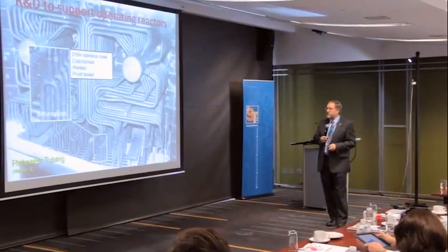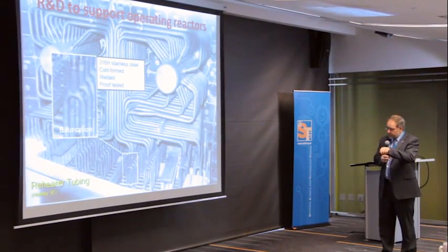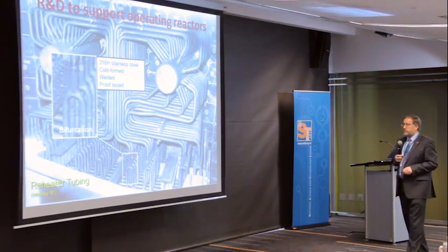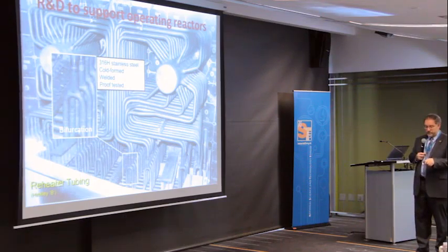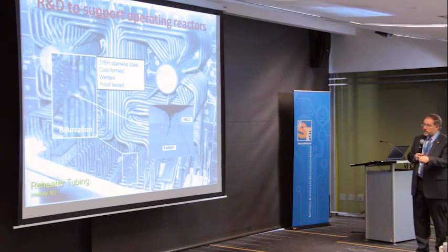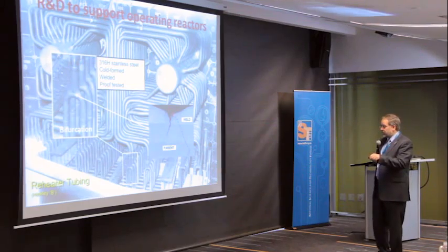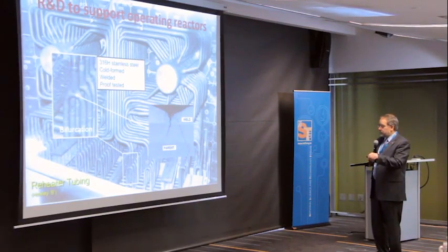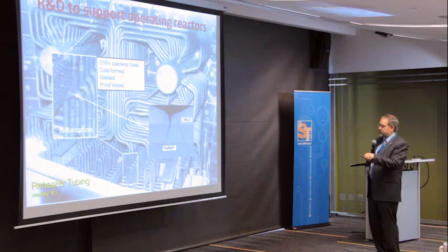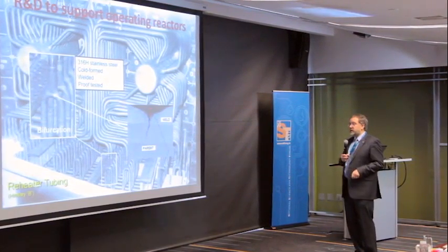It's a bunch of pipe works for an advanced gas-cooled reactor, and in particular, issues down here with the splitting here of this pipe. It's called a bifurcation, and what happens is, at that bifurcation, just adjacent to the weld, the residual stress causes a cracking issue. So that's the actual weld material. No, that's the weld parent material. The residual stress due to the weld causes the stress corrosion cracking to occur just there.